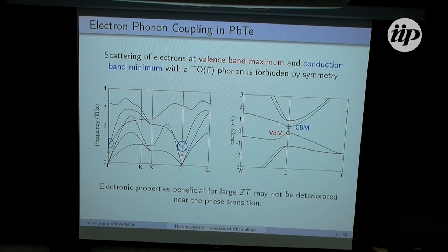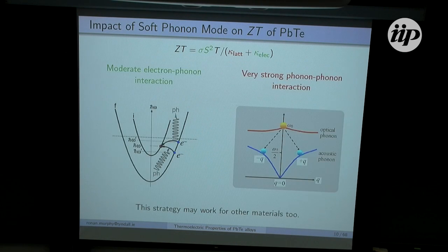However, that's strictly only at the L point. Away from the L point, we would expect there to be some electron-phonon interaction. Just to mention that briefly, you can see the thermoelectric figure of merit again, where these in green are the electronic properties. As I mentioned, away from this L point, there will be some moderate electron-phonon interaction. But as we get nearer the phase transition, we will have very strong phonon-phonon interaction.